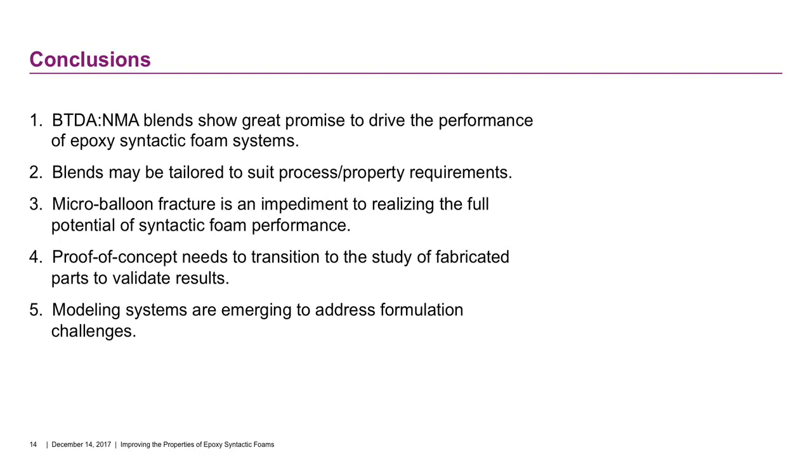So from a formulation standpoint, you may have designed something optimally, but then if you translate that into a processing environment, you may have lost everything by virtue of the fact that you're sacrificing the balloon integrity to mix the materials together. So simple concept, but has a large impact and a large consequence.